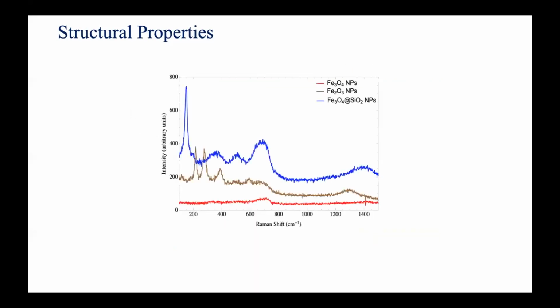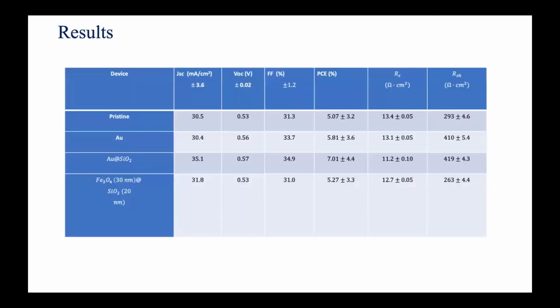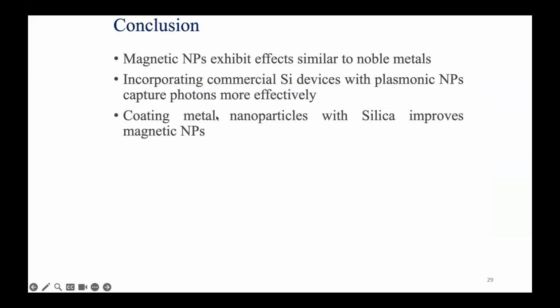Another one was Raman spectroscopy. But now what I want to show is the final result, since I'm running out of time. The efficiency from the pristine one was 5.07. We got the highest efficiency with the gold nanoparticles coated with silica, and the efficiency from the magnetic ones also increased from 5 to 5.27.